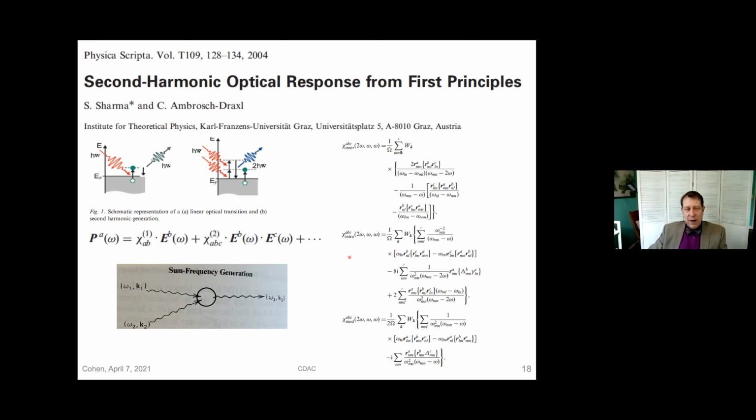Of course, we still have the band gap problem that one has in density functional theory in general, and we've just used a scissors operator, a fancy name for a constant shift, to correct for the band gap error at 0 pressure, and then just kept that constant. So that's an approximation in what we've done. But within that, we are able to calculate the second harmonic nonlinear optic coefficients directly in the ELK LAPW code.